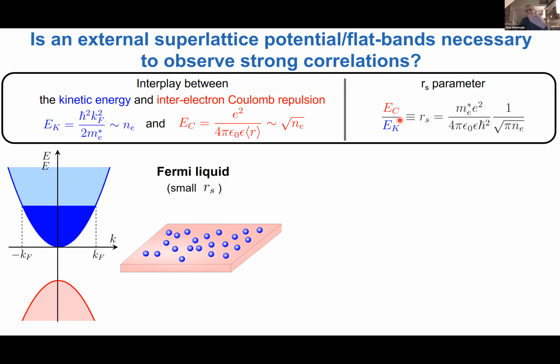Now, a way to judge the potential importance of correlations is to look at the so-called r_s parameter, which is the ratio of the two. And for Coulomb interactions, this parameter scales with the effective mass, so heavier effective mass is good. Inversely with the dielectric constant, so reduced screening is good. These all make sense. And then it scales inversely with the square root of the electron density. So lower density is good for strong correlations, provided, of course, that disorder doesn't destroy the game.